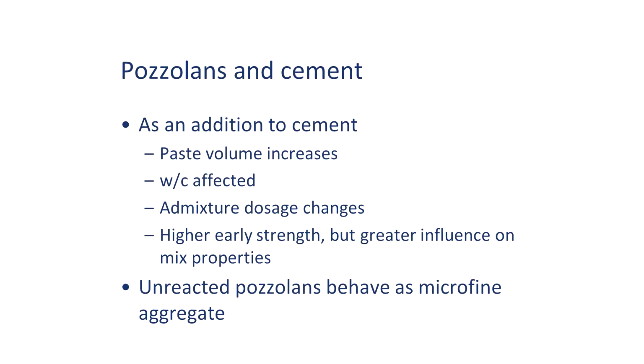Here's the scenario: you add too much pozzolan because you're boosting your cement paste and not changing your water cement ratio. All of a sudden, the concrete gets stiff, and the common reaction is to add more water to the mix to boost the paste, get it more workable, and now your strength goes down because you've had to add more water. The proper thing to do would be to add more superplasticizer to the mix, but that can be problematic too, just by trying to dose it by eye, as I had mentioned before, with segregation and all that.